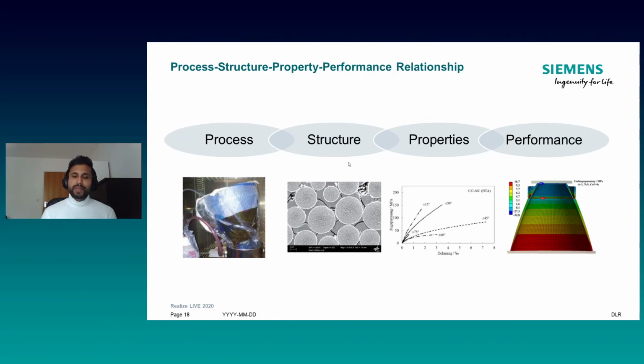And with the help of multi-scale mechanics, if we want to simulate any component at a macro level, let's say this nozzle, instead of adding properties to that particular model, we can directly use these microstructures as properties. Since we have cracks and everything in this particular microstructure, it will directly influence the performance of our material. And as soon as we have established this chain of process, structure, properties, and performance and validated it, I can go back. And if someone tells me I need a material with such requirements, I can go back into the process and tune my process parameters in such a manner that I get the best possible material for any required application.